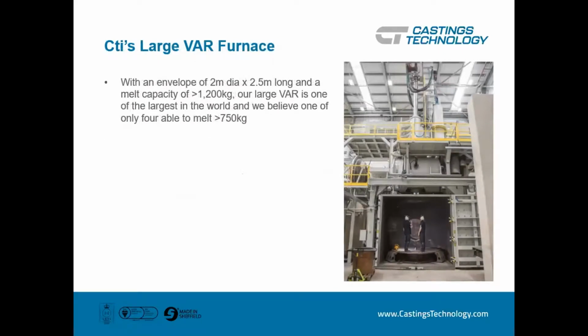Now, when I mentioned the large furnace, it really is large. A couple of ne'er-do-wells out of our melting team are gazing up into the pouring chamber. If you can't see at the back, there are these little people here. That furnace, including the ram, is about 18 meters tall and is housed in an extension to our building. We can just about squeeze 1,250 kilos of molten titanium into the crucible. The crucible sits on this hemispherical door and goes in and out of the melting chamber on rails.